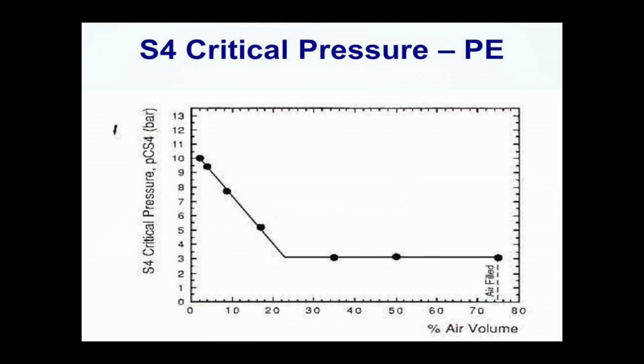This is a plot of the critical pressure as a function of the percent of air. These are data from Dr. Pat Liebers. Most of the time, this S4 test is done in 100% air. That's the easiest way to do the test.